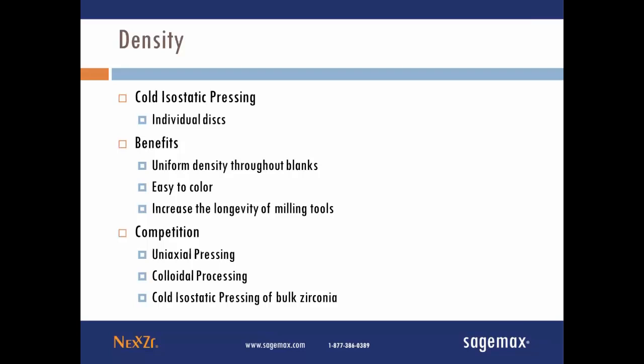Okay, the density. Our material is unique in the sense that we use cold isostatic pressing. Here we're pressing individual discs. Some companies will say that they're isostatically pressing, but they might press a huge log and then cut discs at random intervals or in different dimensions. This doesn't really ensure the proper density throughout the material. Cold isostatic pressing actually allows us to have a very uniform, homogeneous density throughout the blanks.